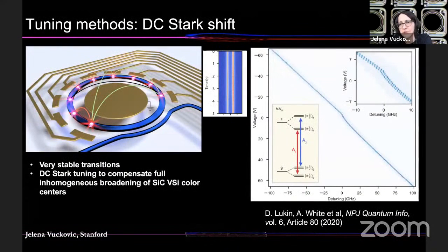And then for silicon carbide, we've shown that we can use DC Stark shift. So we just put electrodes next to the color center and apply voltage, and then we can tune the color center by a few hundred gigahertz. Again, we can compensate for all of the inhomogeneous broadening of the system. And in the process, we're actually not affecting properties of the lines. Line width is small and stability is still pretty good.